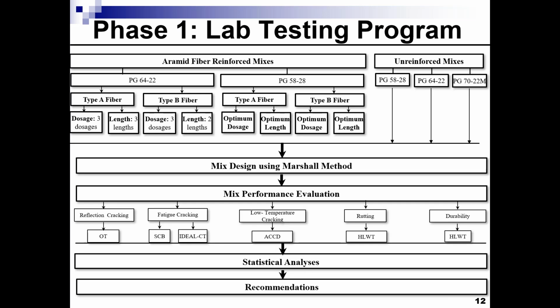This is basically the overview of the testing program. As you can see, it's a very comprehensive testing program where we had different types of binders, but the focus really was on a PG64-22, or basically a neat binder meeting the specification for a PG64-22. This is, I would say, the most commonly used asphalt binder in surface mixes on local roads in Ohio.